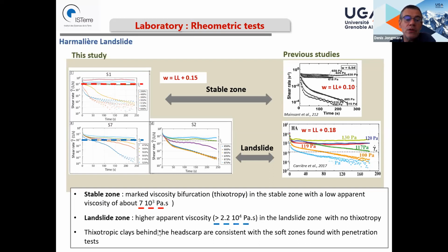So in the stable zone with a low apparent viscosity of this value, which corresponds to this line, to this shear strain rate, the critical strain rate. In the landslide zone, we have a higher viscosity, which is shown here by the dashed blue line, with no thixotropy. And so the presence of the thixotropic clays, of course, with this very rapid change in behavior from solid to fluid, is consistent with the soft zones that you may find with